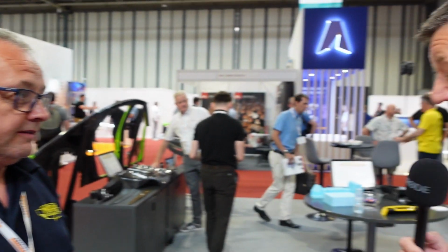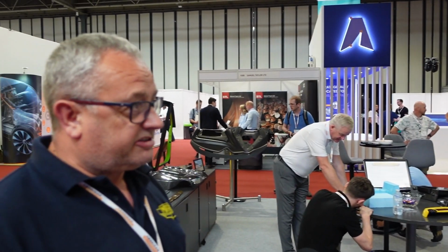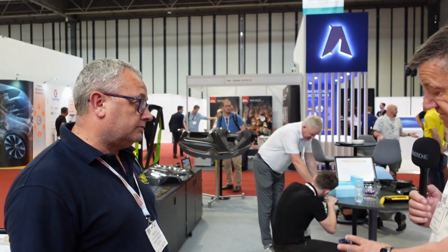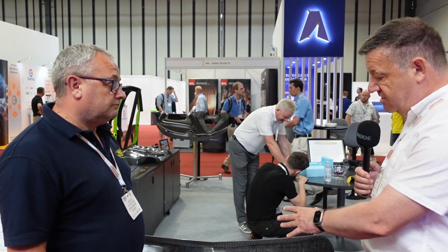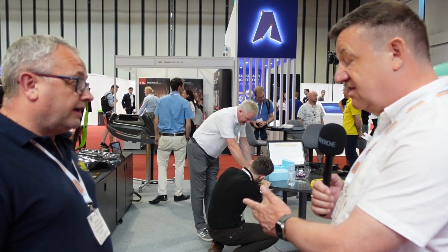Yeah, fascinating. So, in theory, carbon fibre can now be part of a circular economy. Certainly can. When this comes to end of life, could it go through that process again? Yep. You can recycle it again up to 7 times, I'm led to believe. So if that had, in theory, a product life of maybe 20 years in use, 7 times 20, that's reasonable. And obviously every time you do that, you lose a little bit of the strength out of it because you're shortening the fibres. And so that's taken into consideration.